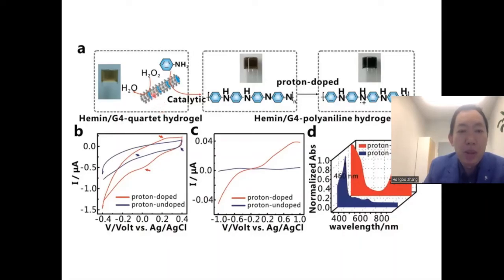And the enzyme used can catalyze some oxidation reaction. So in this reaction, they will generate some hydrogen peroxide. But hydrogen peroxide, you cannot directly detect. You need to convert it to another kind of detectable signal. So in that case, we have coated this with another layer of polymer, and this polymer can convert this hydrogen peroxide signal into a hydrogen ion. So in that case, the hydrogen ion can be detected as an electronic signal.